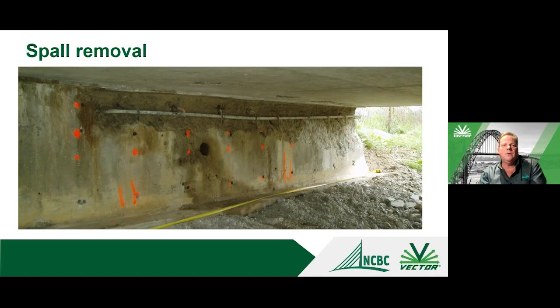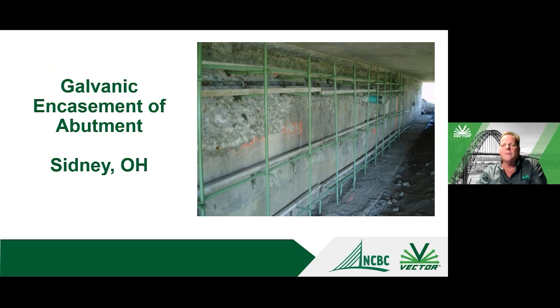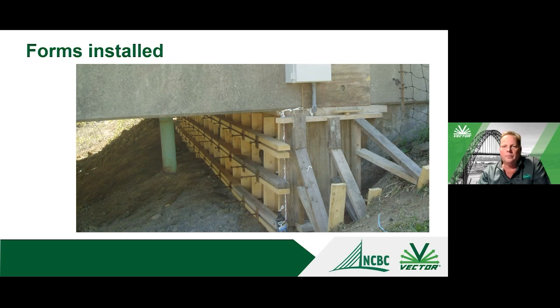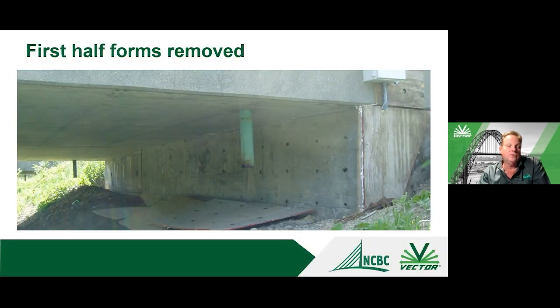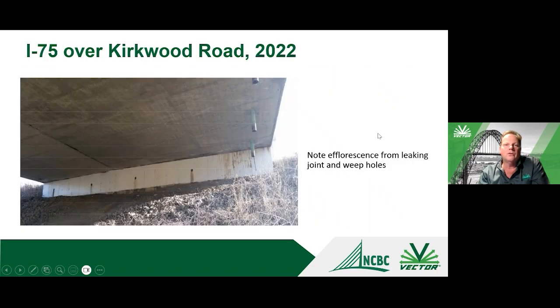Basically, the process here would be to remove the deteriorated concrete. You place your galvanic anodes into the overbuilt section, and then here for Ohio DOT, they use epoxy-coated reinforcing steel just to provide some additional reinforcing in the overbuilt section. Form and pour repairs, and these actually use self-compacting concrete. This was one of the first projects that was done in Ohio. You see the monitoring unit that was installed just to monitor the performance of the anodes over time. If you're interested in that, we have a paper that's been published with a lot of that data. I can share it with you if you're interested.